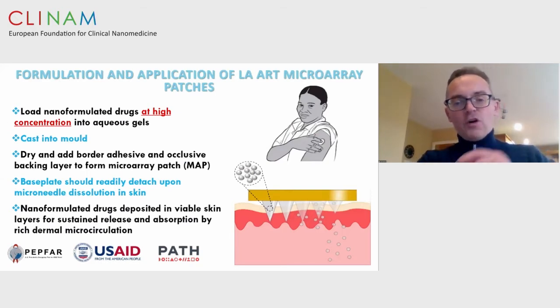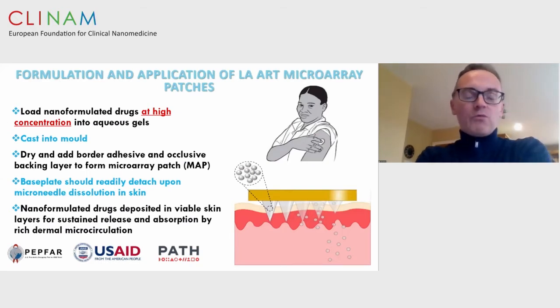So how would we make a formulation like this? We would take our nano-formulated drug, typically made using top-down or bottom-up approaches to produce nanocrystals, and mix that with an aqueous polymeric gel and then cast that into a suitable mold to form the microneedles.